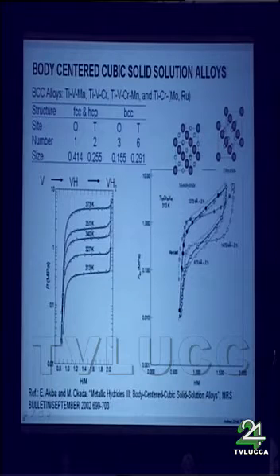The big problem until now is that this first plateau, which isn't shown here, is always at a very low pressure. It's always a very stable hydride. And of course the challenge is to find methods to decrease the stability of this first plateau. By the way, this figure shows you vanadium, from vanadium to vanadium H1 and vanadium H2. That is somehow the model system of a BCC hydride. But I guess we will hear some more information about that from Etsuo Akiba.